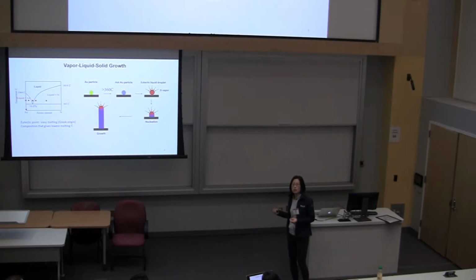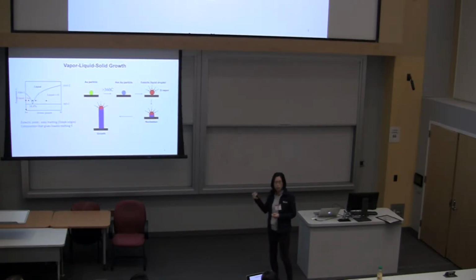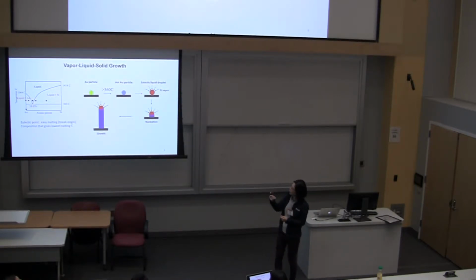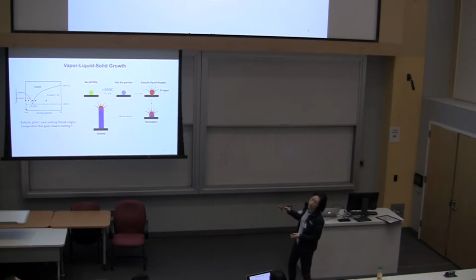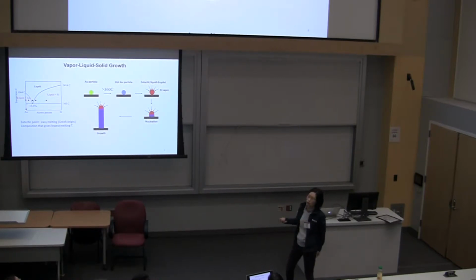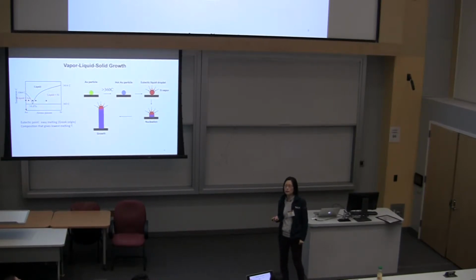So usually for silicon nanowires, gold particle is a terrible catalyst to use because gold really kills the transport properties in silicon nanowires. So people have tried using other ones like copper or palladium. You can look at the binary phase diagram yourself between silicon versus some other metal, and basically as long as the eutectic point is low enough and there's silicon that will be dissolved, then it should work as a catalyst. Yeah.